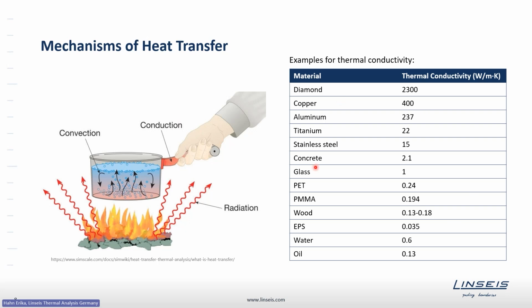Here you can see in this table some examples for thermal conductivity, where you can see that the range is very huge. So, for example, insulation materials have a thermal conductivity even below 0.1 watt per meter Kelvin, whereas metals have a quite high thermal conductivity, and diamond is one of the materials with the highest thermal conductivity of about 2,300 watt per meter Kelvin. So it is a challenging task to be able to measure all of these thermal conductivities.